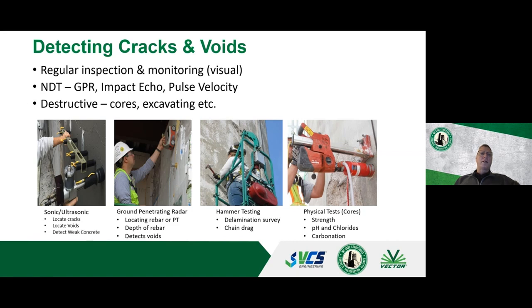Another tool, non-destructive, NDT is non-destructive testing methodology, is either GPR or impact echo or pulse velocity, and we'll talk a little bit about that. And then some of the destructive manners which you can use for cracking is coring, which you can see on the right side where you're actually drilling it in. How deep does that crack go? And it kind of gives you an idea along those lines.